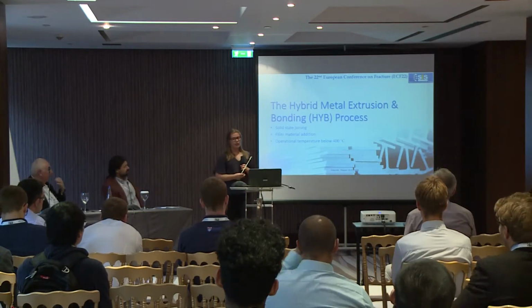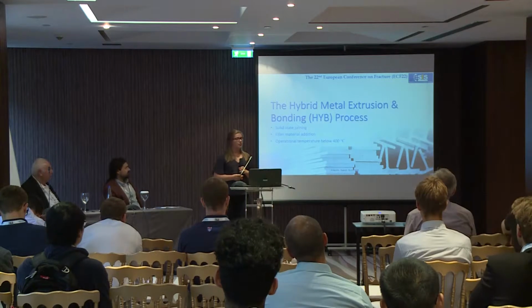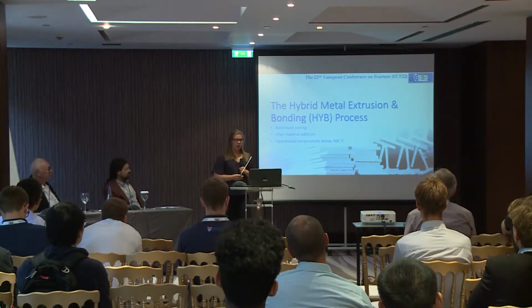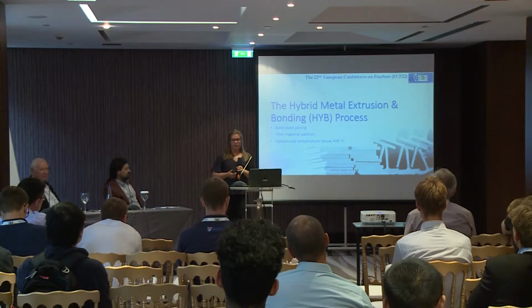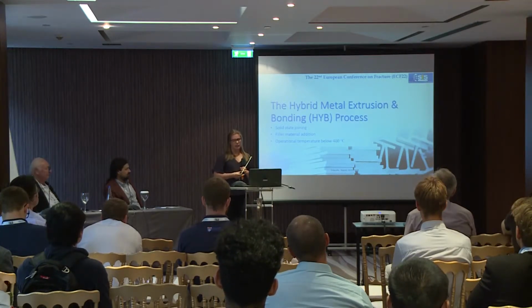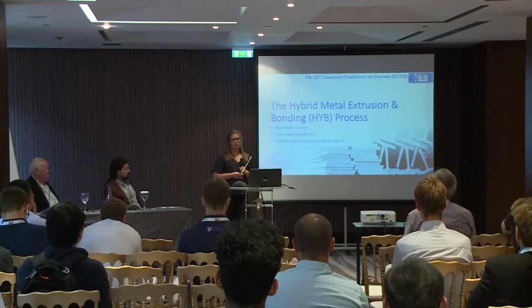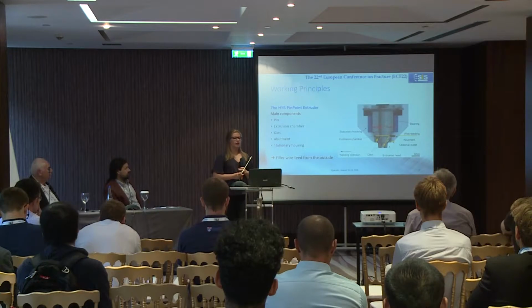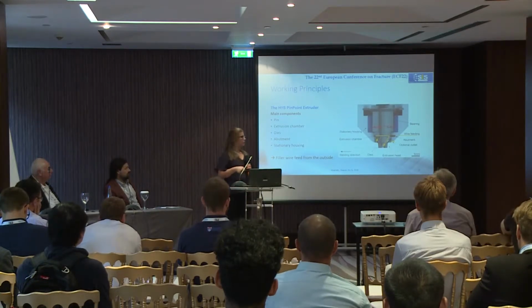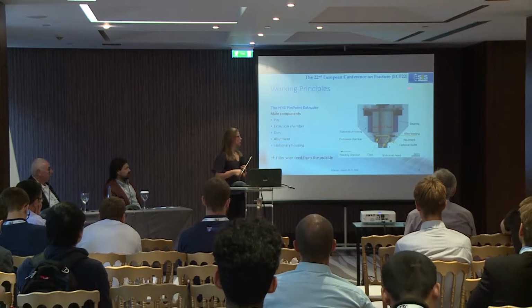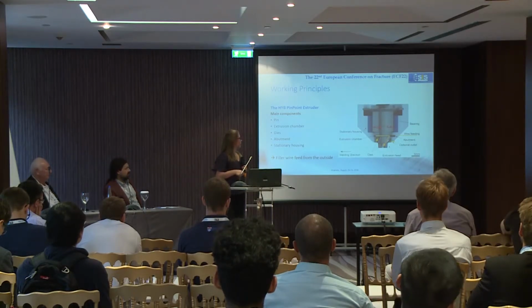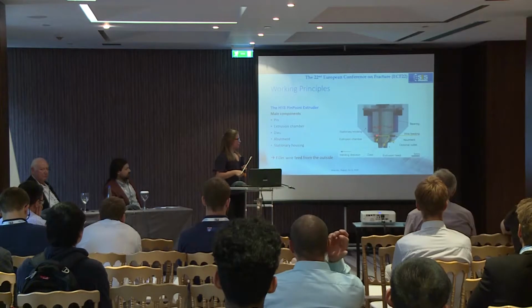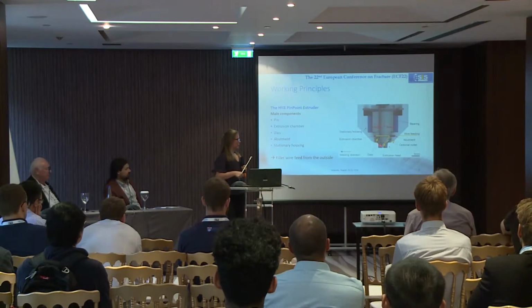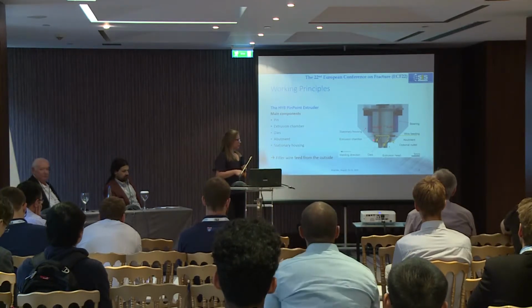The HYB process is a new solid-state joining technique which is mainly invented for aluminum alloys. It uses a filler material and plastic deformation to create joints at operational temperatures below 400 degrees. The current version of the extruder is the HYB pinpoint extruder, which you can see here. The extruder is built up around this rotating pin with an extrusion chamber, an extrusion head with open dies in the lower end, an abutment, and a stationary housing.